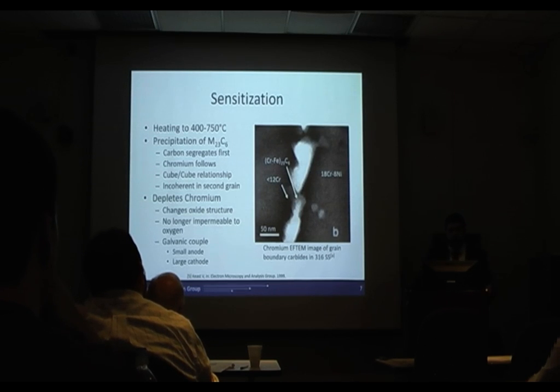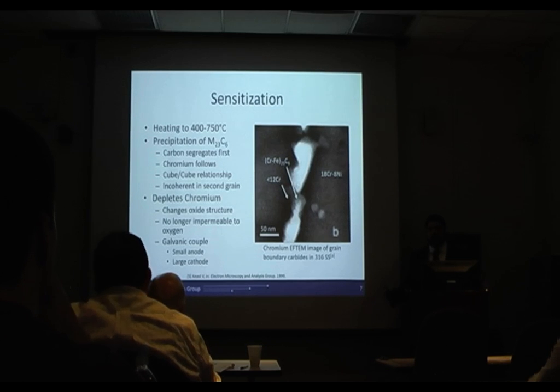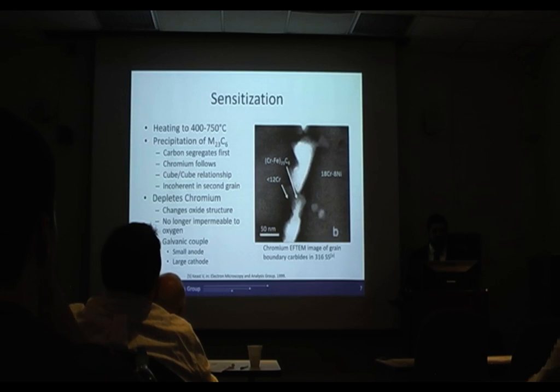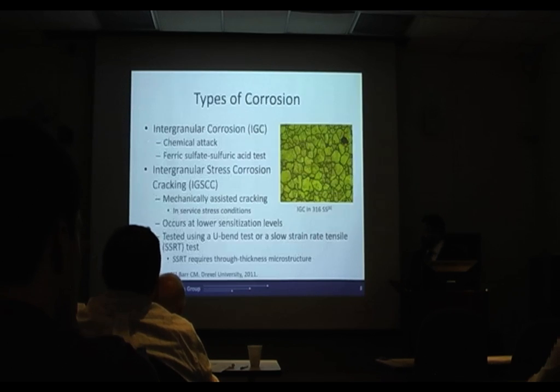But the real problem with this is that you now have a galvanic couple between your very large grain area with the passive layer, which is a large cathode, and then a very small anode area around the grain boundaries, which is vulnerable, so you get very aggressive attack there.